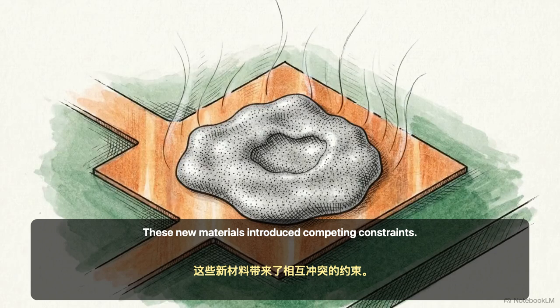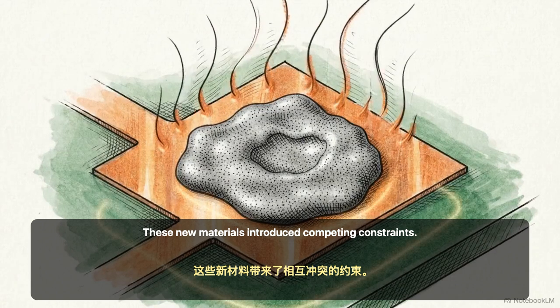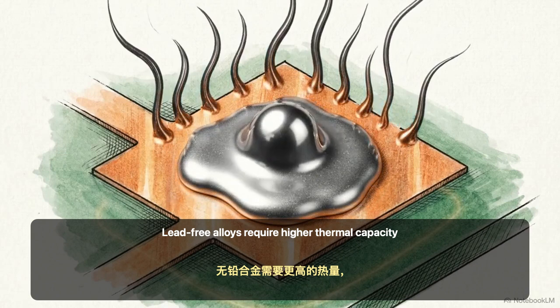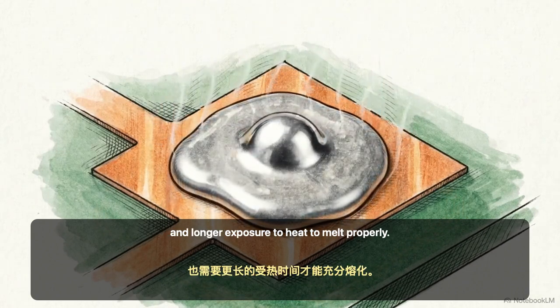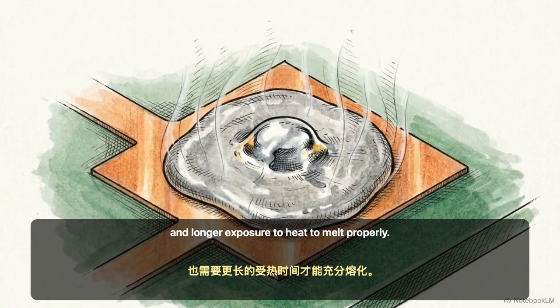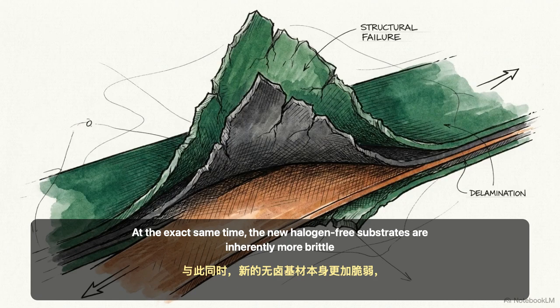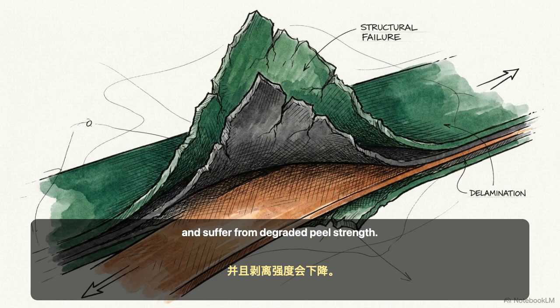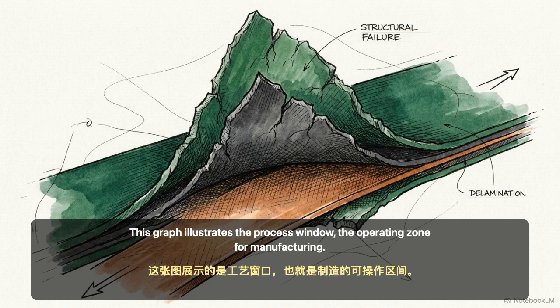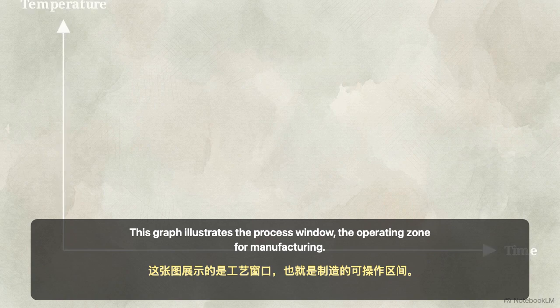These new materials introduced competing constraints. Lead-free alloys require higher thermal capacity and longer exposure to heat to melt properly. At the exact same time, the new halogen-free substrates are inherently more brittle and suffer from degraded peel strength. This graph illustrates the process window, the operating zone for manufacturing.